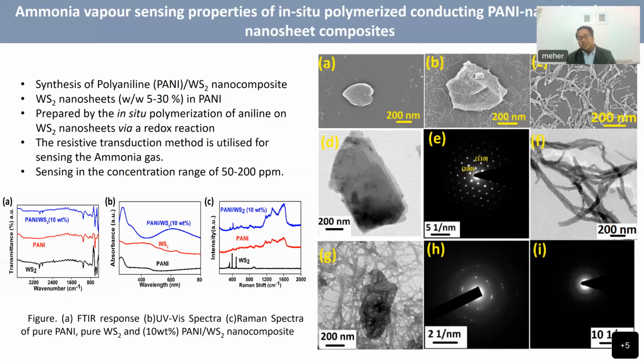If you go from micro to nano, the surface to volume ratio is greater by a factor of 1,000. So nanoparticles are always good to have if we want to do applications like sensing. So what we did, we prepared two-dimensional nanoflakes of tungsten disulfide, the metal dichalcogenide counterpart of graphene. And then we also made polyaniline nanofibers, and we made a composite of these materials by chemical methods.